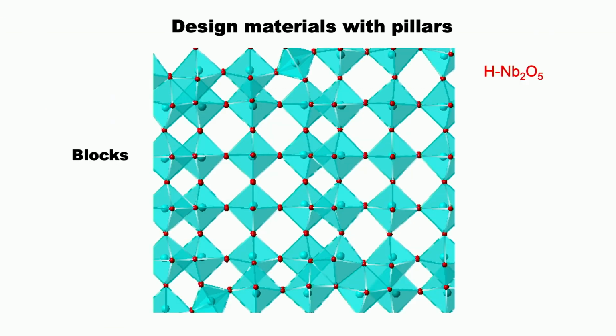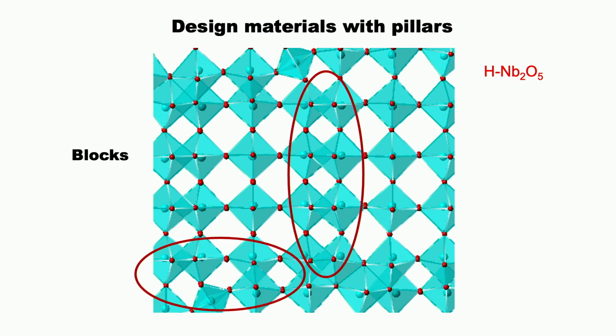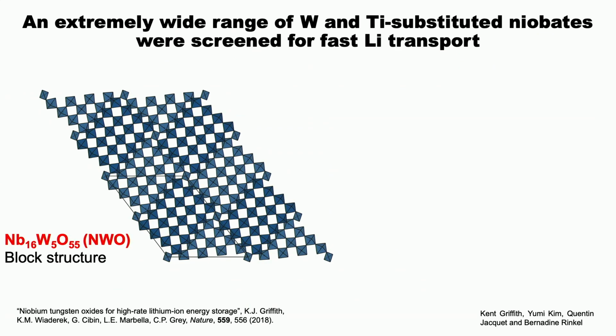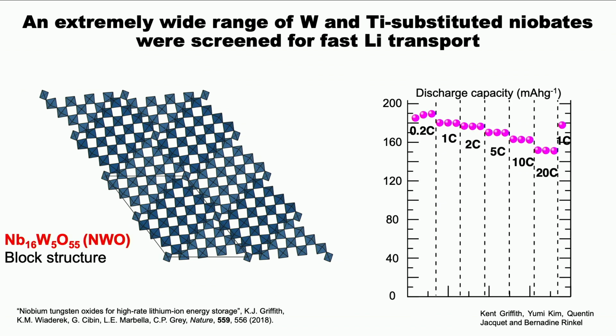And you can do it in 2 dimensions, and that's when you get this H-Nb2O5 phase, and you form these blocks. And again, the lithium is really rigid there, and you get, in principle, very rapid lithium mobility. And so that's what my former student Kent Griffith did. He went through a whole series of different compounds, and the best in class he discovered in his PhD was this niobium-16 tungsten-5 O-55, which for obvious reasons is abbreviated to NWO. And so this has a block structure of 4 by 5, and it has a very high rate.